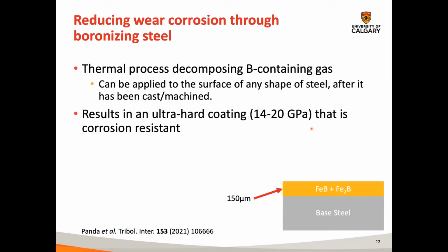So the idea from Endurance Technologies was that you could improve the erosion corrosion performance of steel or other metals by making a boronized layer or coating on top of the steel. Basically what they have is a huge furnace that you can put pipes in of very large sizes that can be put on an 18-wheeler truck, or you can even make a heat exchanger and coat the inside of your heat exchanger with this process. This process results in an ultra hard coating that is 14 to 20 gigapascals. And iron borides are in general corrosion resistant, so you enhance the corrosion resistance of the steel.